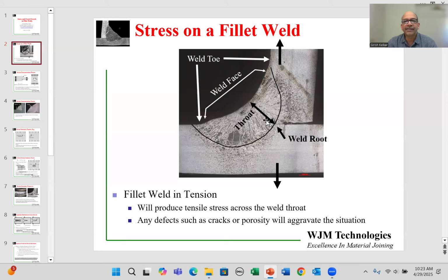Essentially, if you apply a tensile stress as shown by these two black arrows, as in trying to pull the weld apart, the stress is going to be transferred through this throat as the bottleneck from one component to the other. The weld I've shown does not have any defects on the inside, but could potentially have, say, cracks and porosities, which will, of course, aggravate the situation.